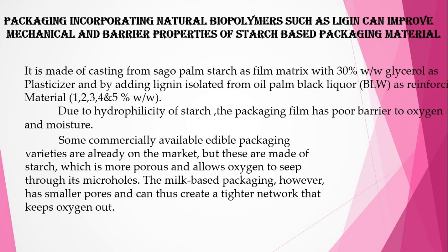Packaging materials incorporating natural biopolymers such as lignin are found to improve the mechanical and barrier properties of starch-based packaging. These are made by casting from Sago palm starch as the film matrix, with glycerol as a plasticizer, and adding lignin isolated from oil palm black liquor as reinforcement. This composite is made from Sago palm starch plasticized with 30% glycerol and reinforced with lignin. Due to the hydrophilicity of starch, the packaging film has poor barrier to oxygen and moisture. Some commercially available edible film varieties made of starch are more porous and allow oxygen through their micro holes.